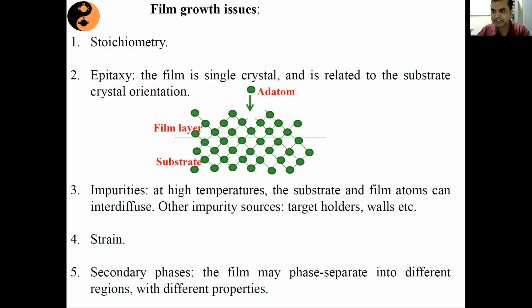And after attaining the thermal equilibrium, it hops on the substrate surface from one side to another side. Now just imagine a situation that your substrate temperature is very, very low, and the evaporant which is coming on the substrate, when it arrives on the substrate, it looks at, okay, there is not sufficient energy available with the substrate surface. So it transfers all its energy in maintaining the thermal equilibrium with the substrate itself. And after that, it does not have sufficient energy available to hop or to move on the substrate surface from one side to another side.